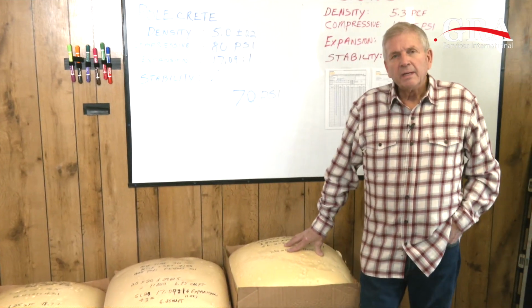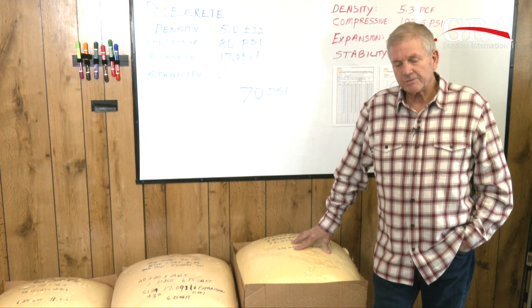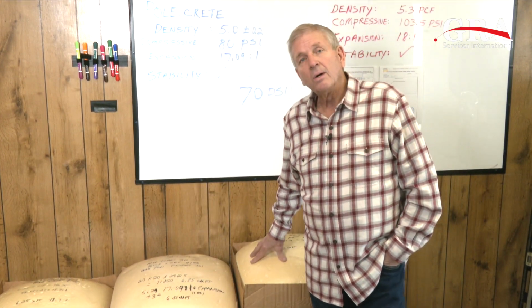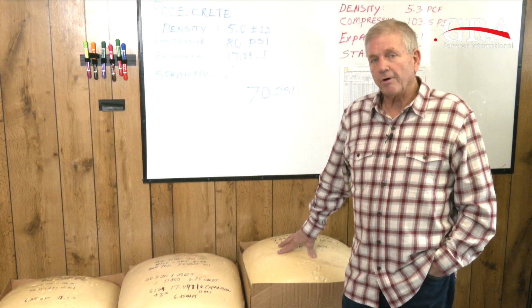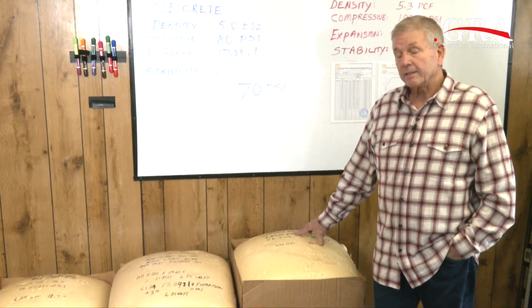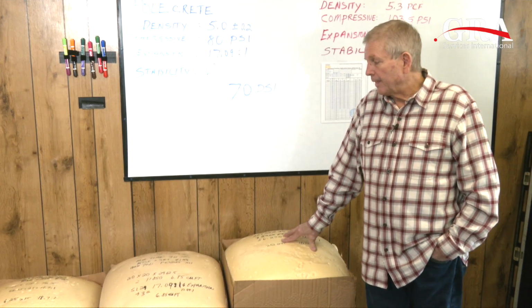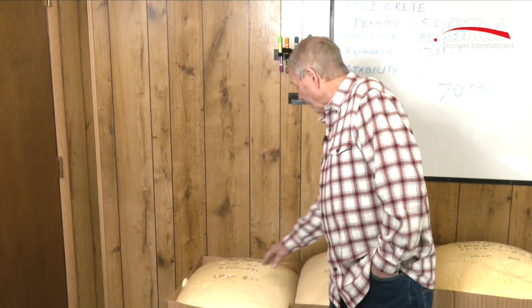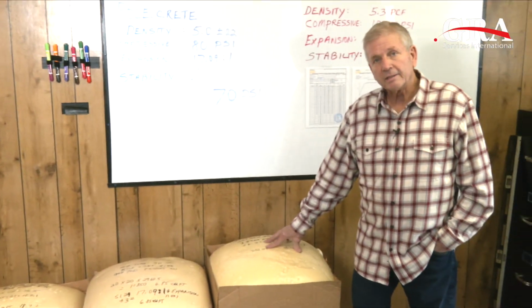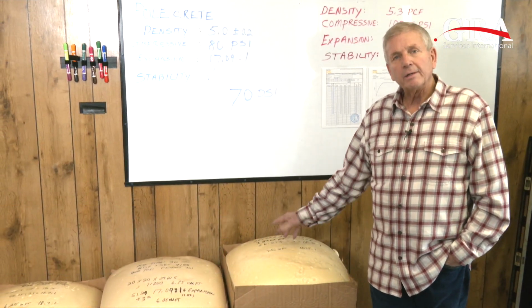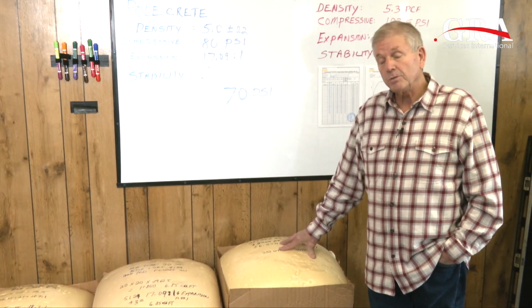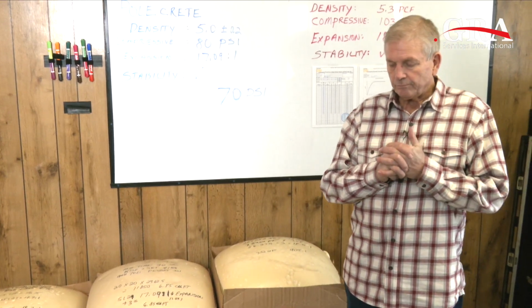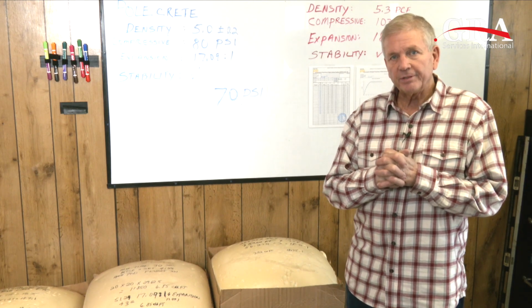Now here's what we like to point out. In our literature, we specify that our 2.5 gallon kit will yield you at minimum 6 cubic feet of foam. We also say that our 3-gallon kit will give you 7.25 cubic feet of foam. What we have consistently identified is that with very similar expansion ratios for the two kit sizes, the 2.5 gallon yields 6.25, a little boost over the 6.0, and the 3-gallon kit will give you 7.52, and we specify that it'll give you at least 7.2 cubic feet. So from that perspective, with a review of everything that we've looked at today.